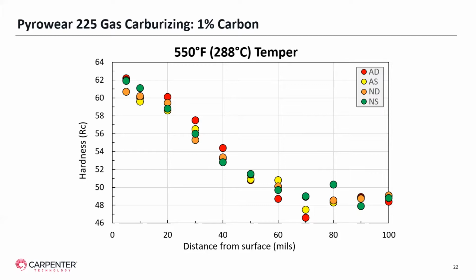if it has an A, we did an intermediate austenization after we carburized and before we tempered. If it has an N as the first digit, as the orange and the green dots indicate, that means we did not give it an intermediate austenization. D and S in the second digit simply mean the material was either double tempered or single tempered. So we looked at these different variants at a number of different tempering temperatures.